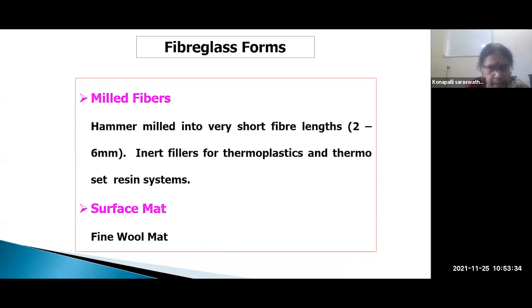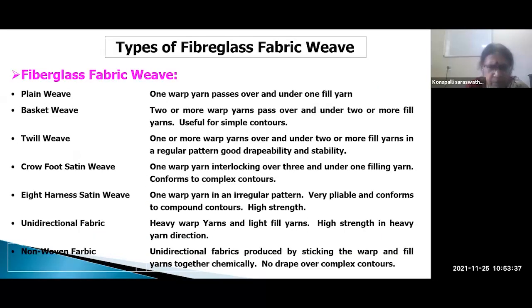And various fiberglass weaves are there, like plain weave, like the clothes we wear, one warp over and under the fill. And basket weave, twill weave, then 8H satin weave. Satin weave means it will be like our satin fabric, very flexible. So one yarn will be in the warp direction in an irregular fashion. It will be very high strength and it conforms to the mold. That is why generally we use 8H satin weave in all our fabrics. Then unidirectional fabric, as I told you, has all the fibers in the warp direction. There we get very high strength, and in the other direction we just have to bond the fibers with some polymer fibers. So various weaves are there.